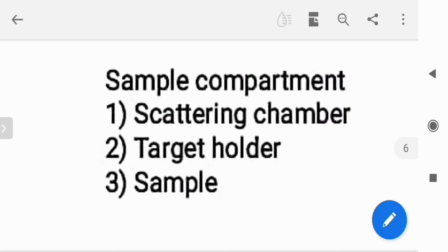The pellets are then used as the sample. The incident source covers around 10 to 50 micrometers of the sample, so only that much area is covered. A diameter of around 1 to 10 millimeters is representative of the whole sample. So the sample must be homogeneous, and if it is not, we make it homogeneous by grinding it into fine powder, mixing it with some grade carbon powder, forming pellets and analyzing those pellets. That is the requirement of the sample in PIXE.